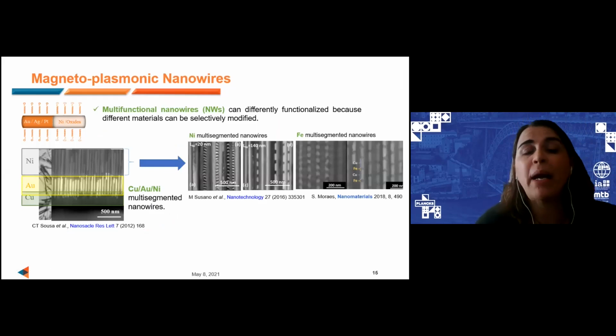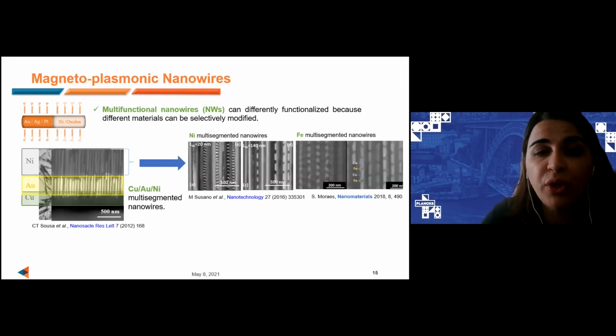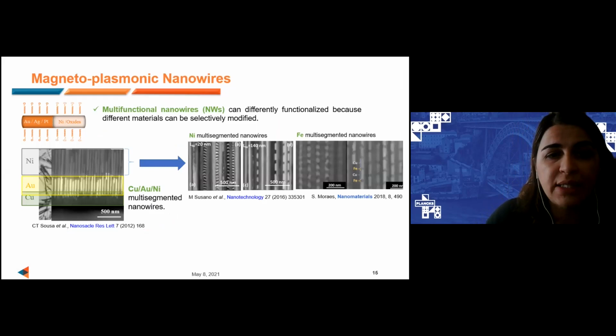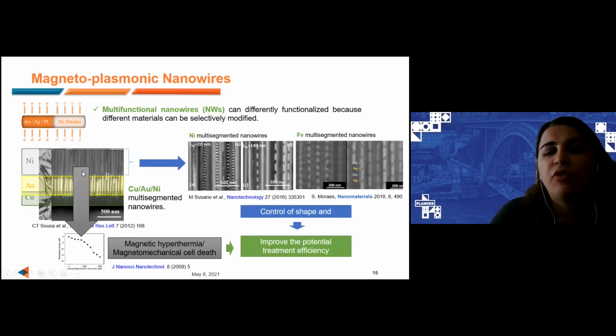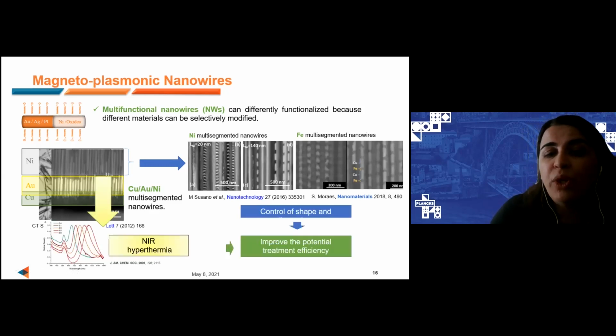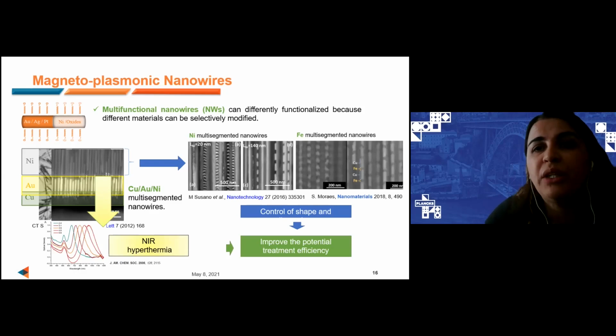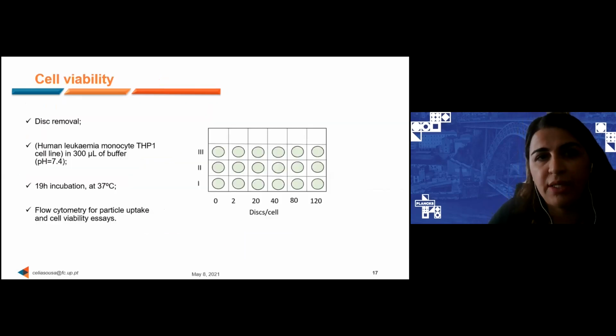We can also combine different materials in the same nanowire. For example, here we have a nanowire with a magnetic and a plasmonic part. These kinds of nanostructures can be used for magnetic hyperthermia or magnetomechanical cell death, combined with near infrared hyperthermia, since we also have a plasmonic material in our nanowire. Also, both materials can be functionalized with different molecules on the surface.